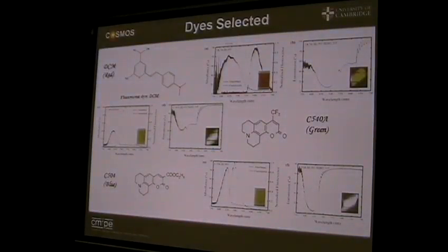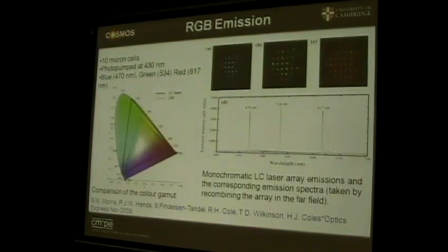And so we wanted to make, as I said, a red, green, blue laser. And those are the different coumarin dyes and their structures that you can use to make these laser systems work. But that is a red, green, blue laser array. Okay? In this case, because I wanted purity of spectral colour and bands, you make a 3-compartment cell, just put in a polymer spacer. And in the far field, that's what you see. Blue light at 470, green at 5, whatever it is, 3-4, and red.